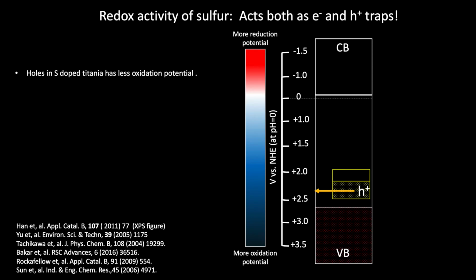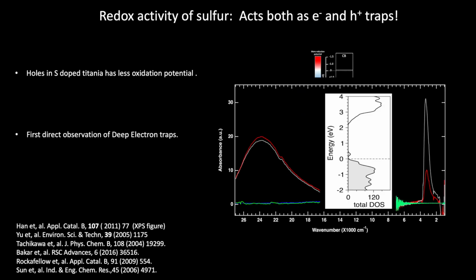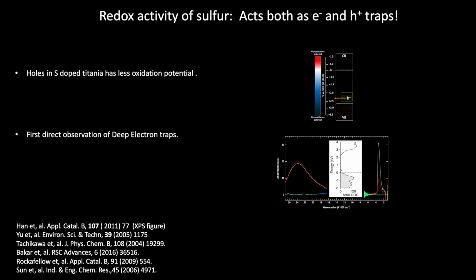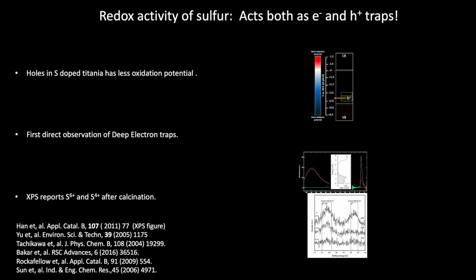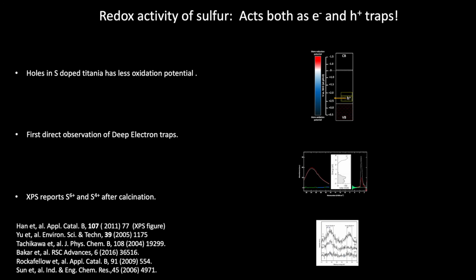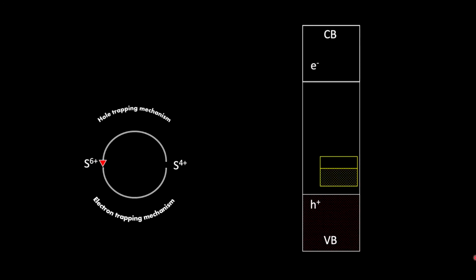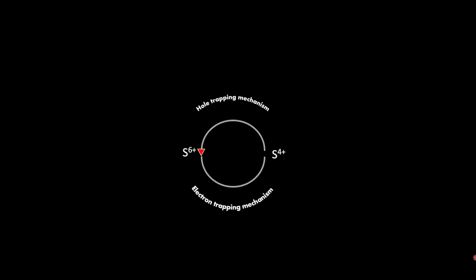By considering these reports and our evidence for deep electron traps, along with XPS results showing signals for sulfur with 6 plus and 4 plus oxidation states, we can imagine a dual nature for sulfur states in titania. These states could act as electron traps by accepting electrons from the conduction band and reducing to 4 plus oxidation states. And then, by donating electrons to the holes in the valence band, they can act as hole traps and reoxidize to 6 plus oxidation states. And that brings us to the end.